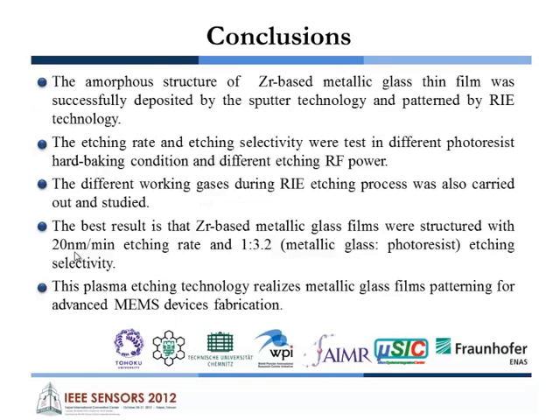So this is the conclusion. The amorphous structure of Zr-based metallic glass thin film was successfully deposited by the sputter technique and patterned by the RIE technology. The etching rate and etching selectivity were tested under different photoresist hard baking conditions and different etching power. Different working gases during our RIE etching process were also carried out and studied. The best result is that the Zr-based metallic glass thin film was structured with a 20 nanometer per minute etching rate and 1 to 3.2 etching selectivity for metallic glass to photoresist.